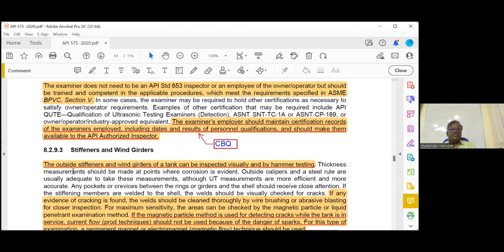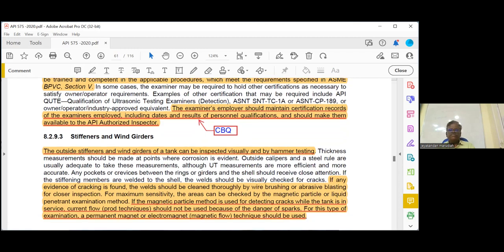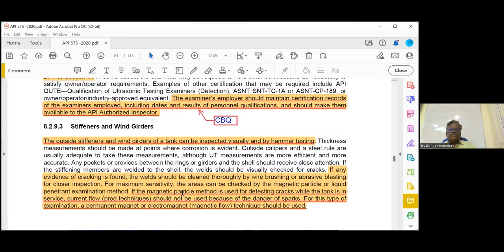Then highlight the stiffeners and the wind girders, first line. The outside stiffeners and wind girders of a tank can be inspected visually and by hammer testing. Then the last 3 lines are important, highlighted. If the magnetic particle method is used for detecting cracks while the tank is in service, current flow prod technique should not be used because of the danger of sparks. For this type of examination, a permanent magnet or electromagnetic flow, that is yoke technique, should be used. Prod is not allowed when the tank is in service.